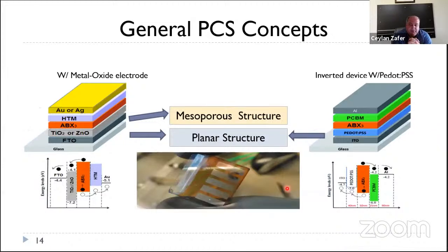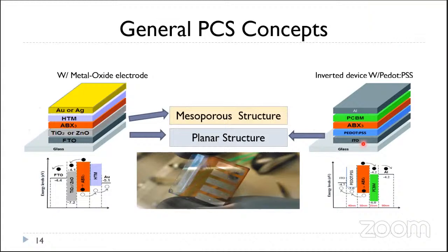If I'm going to talk about the geometry of the solar cells, there are different geometries, but mainly two geometries are accepted for the research cells: the NIP geometry and the PIN geometry. There is a slight difference between the electron and hole transporting materials, and it's an inverted structure. This depends on the production facilities. If you'd like to make production at low temperatures, usually the PIN geometry is acceptable, because using this geometry, you don't need to go to high temperatures like 400, 450 degrees to sinter the metal oxide layer, because there is no metal oxide layer in the structure. And you can use this geometry on plastic or flexible substrates like PET or PEN.